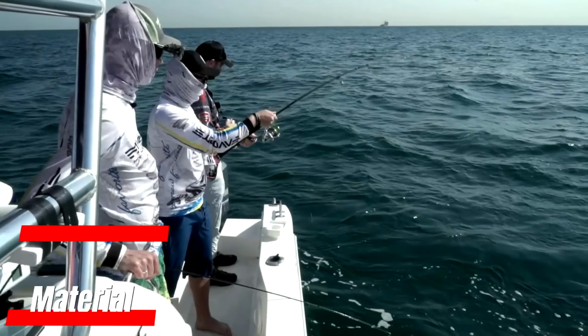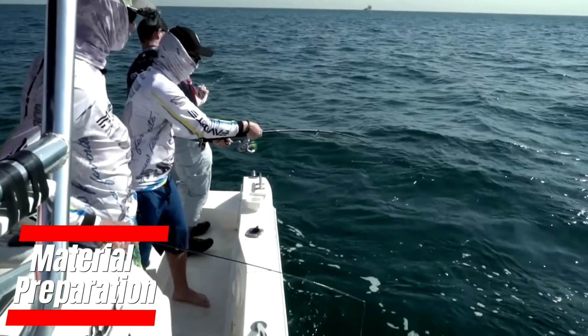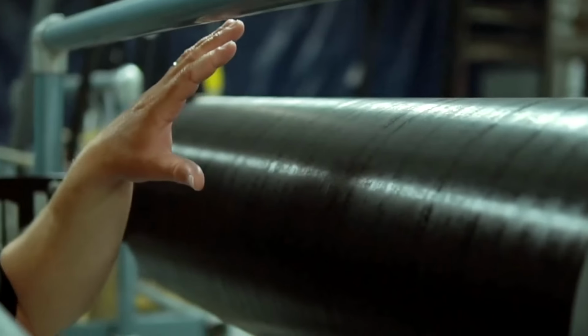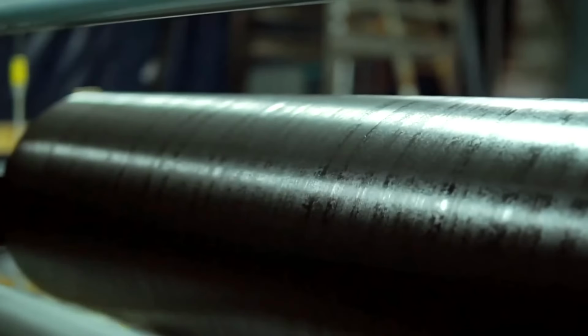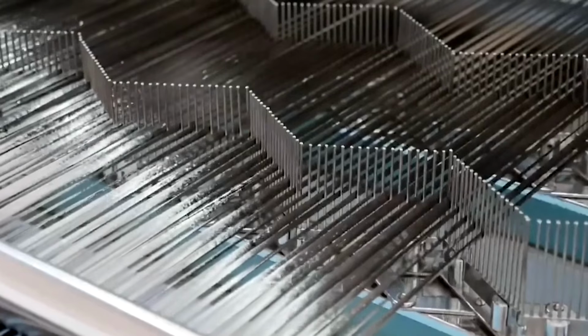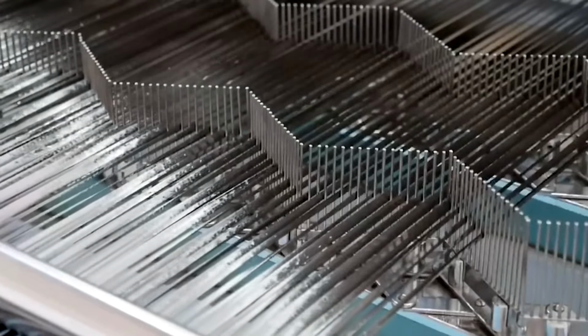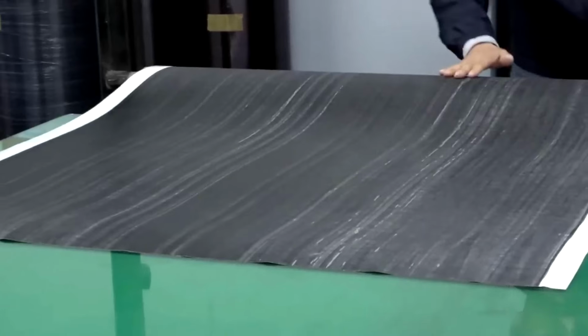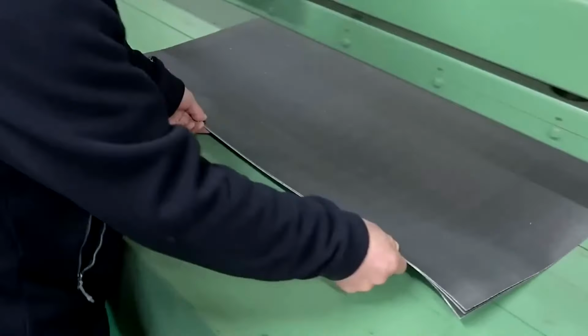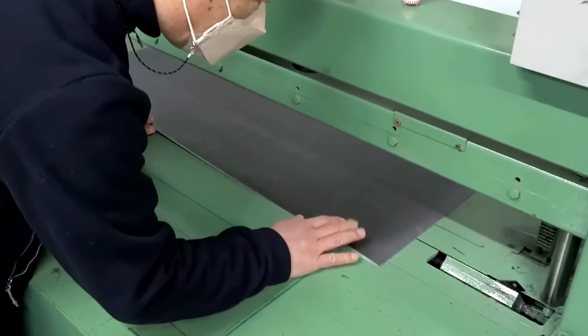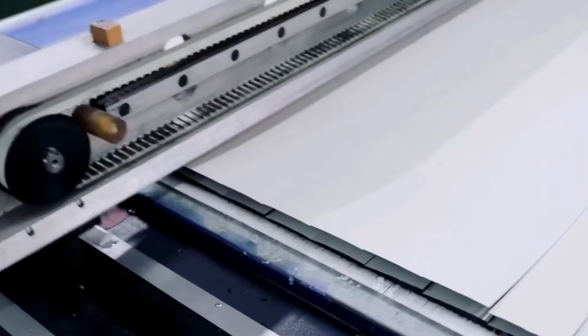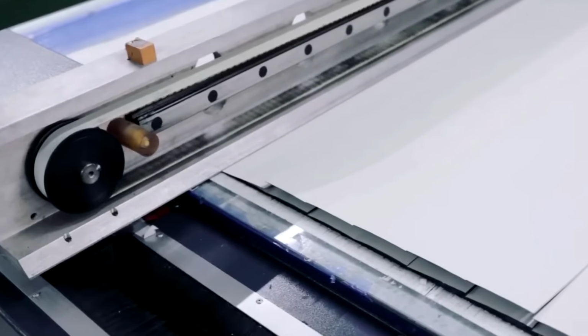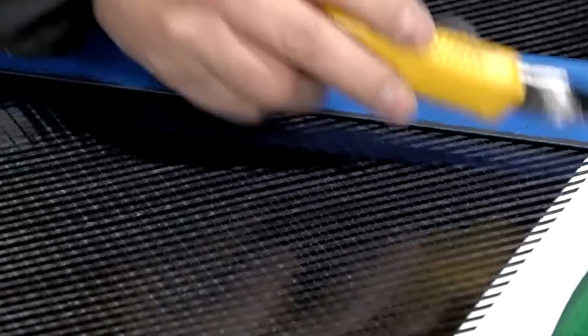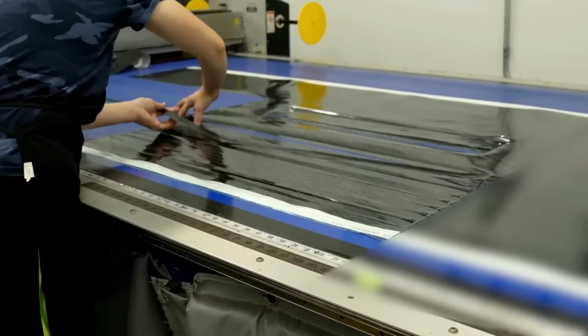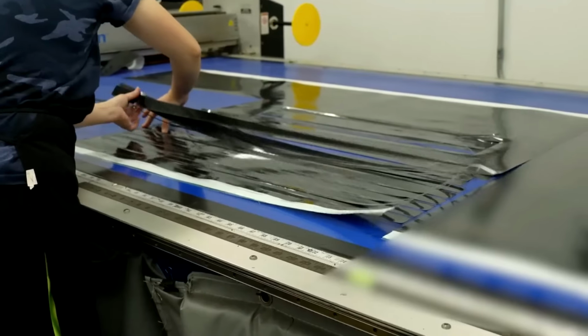This precise cutting geometry controls exactly how force travels along the length of the finished rod when it eventually bends under a heavy load. It gets more complex further on. A single piece cut off by just a small fraction of an inch can shift the entire flex point of the rod, ruining its mechanical properties. One can see how the blades move with millisecond accuracy to avoid any deviation in the fiber orientation. This concludes the preparation of the fundamental components for the rod structure.